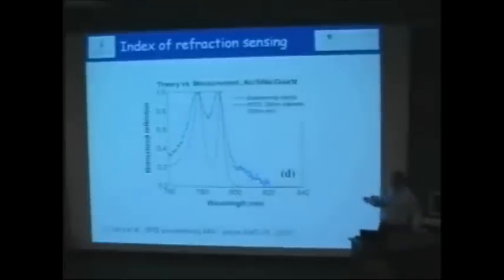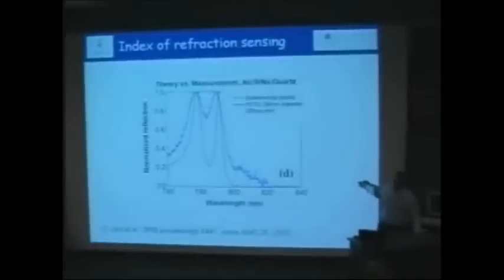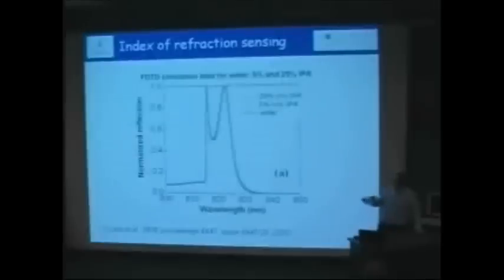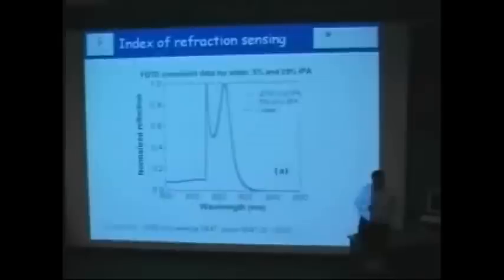So the better the fabrication, the more uniform is your device, the better you're going to get the sensitivity. It's always a combination of movement of the peak, which we call sensitivity, and also the quality factor, how narrow is the peak. So this is one example. But even with that, you could see we made a measurement where you could measure a peak moving by changing the index of refraction by blending water and IPA, and you could see this change. So that was a good effort that we did, and then we went back to design and make better devices.